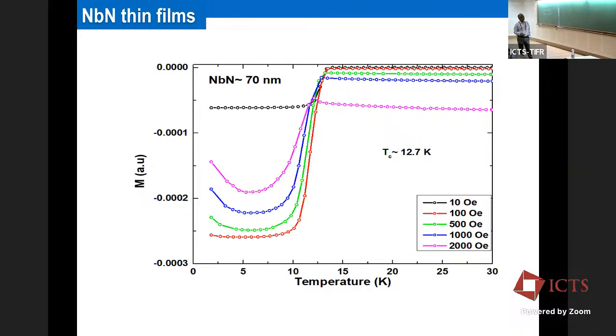And then we did this ZFC MT, and there we can see that for the 70 nanometer thin film, we are having a TC of around 12.7 Kelvin, up to 2000 Oersted. This went up to like a 10. So as you see, with the magnetic field we are applying, the TC goes down. So up to 10 Kelvin we achieved in here. These things were while we were optimizing our parameters, right?